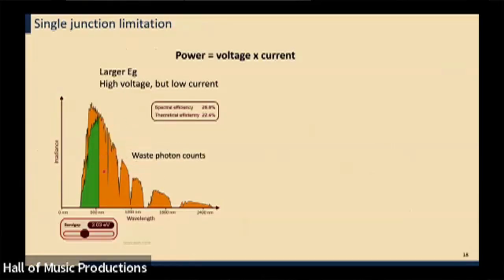I mentioned a couple of times this idea that solar performance can be enhanced when we no longer rely on just a single band gap. And I want to explain where that comes from and then where the opportunity to make multiple colors of band gaps derives from. So if you want to look at the solar spectrum, which is the very broadband orange distribution here, spanning, as you can see, the visible, the near infrared, and the short wavelength infrared, if you place the choice of band gap, let's say at 620 nanometers at about 2 eV, as has been done here, well, we'll be able to absorb those colors above that band gap, so to the blue of that, so to the left on this spectrum.